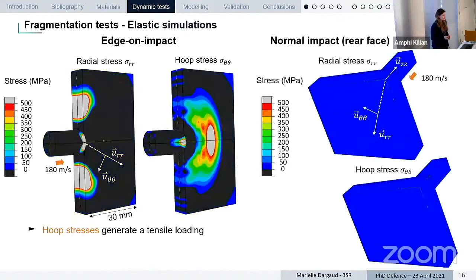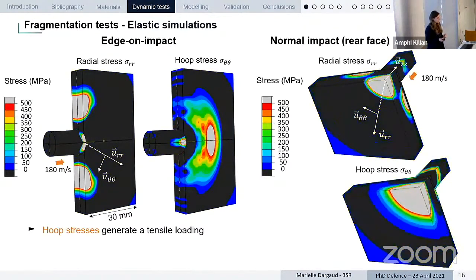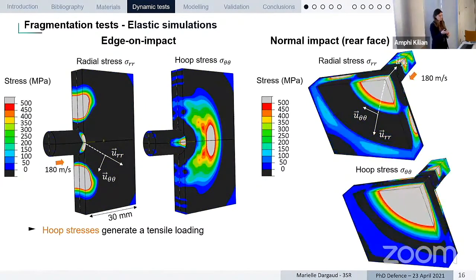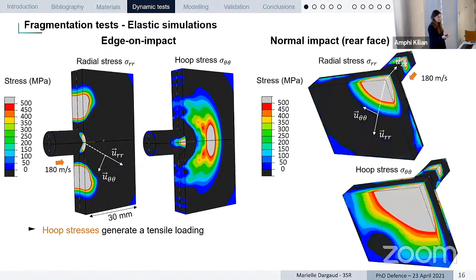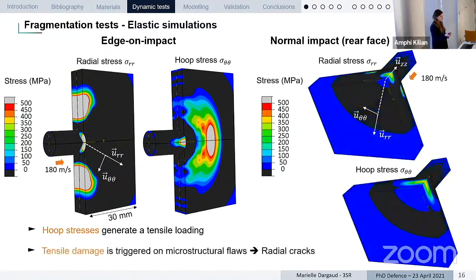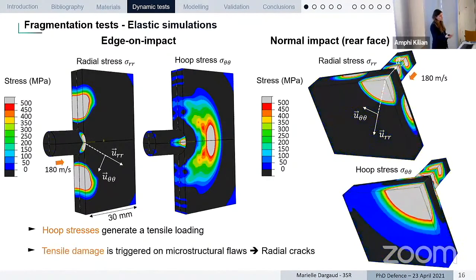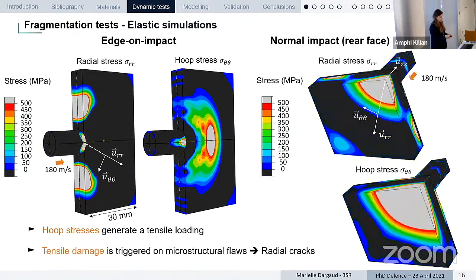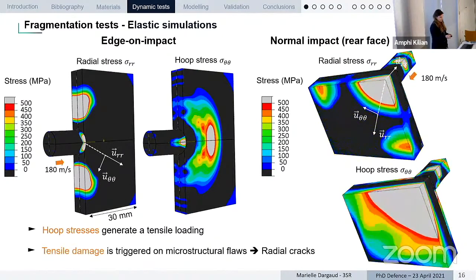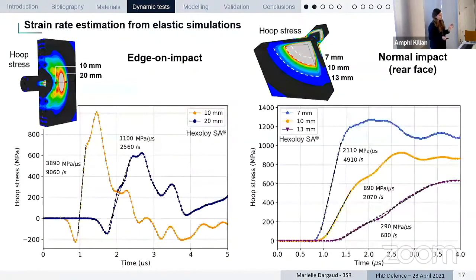The second type of impact that we've done is normal impact. So here you have a quarter of the system, and we are looking at the rear face of the ceramic. We can see that in this configuration, we managed to induce a tensile loading at the rear face of the ceramic. So it is in this position that we are going to study the output data.